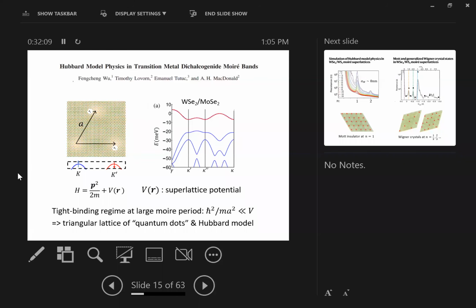So what is the role of the other layer? Well, it's just to cause a superlattice. When you put the two layers together, there's lattice mismatch, and there's superlattice formation. Structurally, the layer itself is corrugated in a periodic fashion. Because of that, the valence band top is spatially modulated in the WSe2 layer. This is modeled by just a simple parabolic dispersion plus a periodic potential.